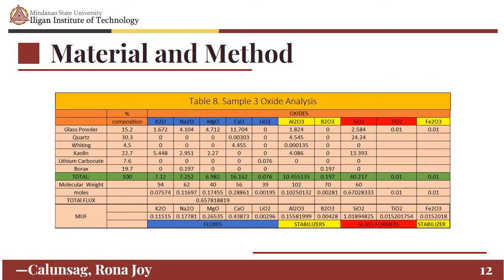Table 8 shows the sample 3 oxide analysis, which was fired at 1100 degrees Celsius. Given the percent composition, we are able to obtain the fluxes, stabilizers, and glass formers. For the fluxes, the K2O has 0.11515, the Na2O has 0.17781, MgO has 0.26535, the CaO 0.43873, Li2O 0.00296.